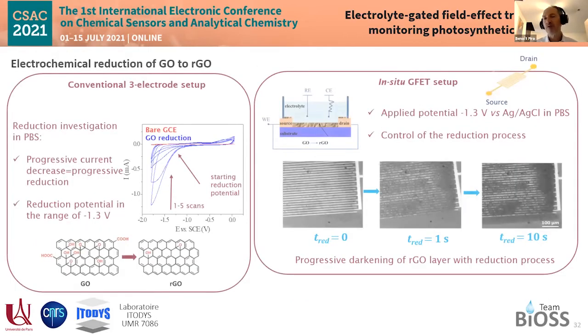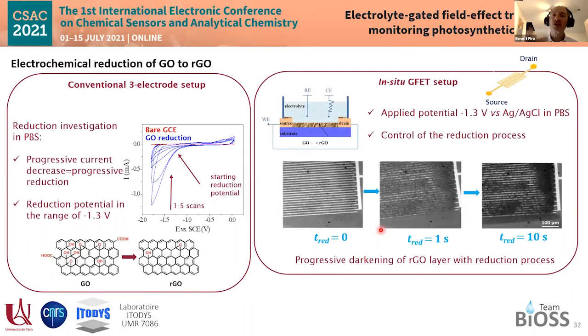And then, because graphene oxide is not conductive and not interesting, we electroreduce graphene oxide in situ on the transistor by short-circuiting the source and drain contact and apply a reduction potential. Then the graphene oxide becomes darker and darker depending on the yield of reduction.